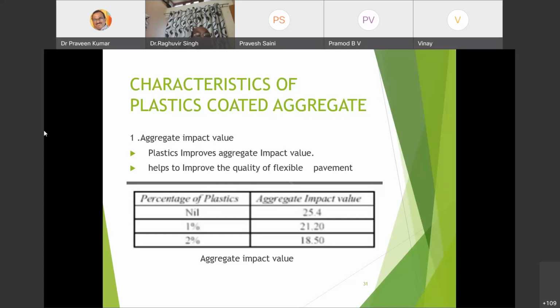Now the percentage of plastic is increased up to 2%. Again the impact value of the aggregate mix reduces, to 18.5%. This means the hardness and strength of the aggregate is improving in that case.